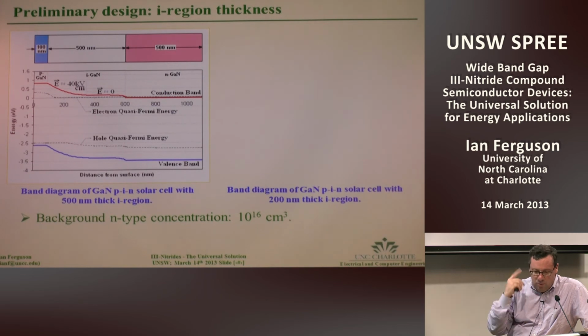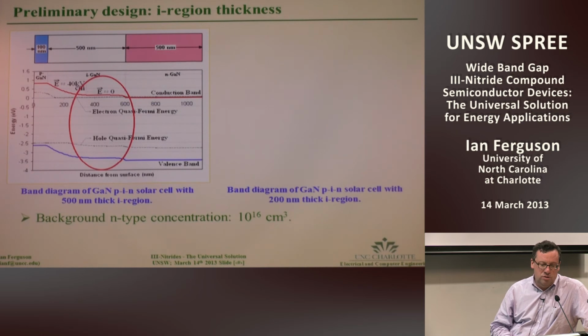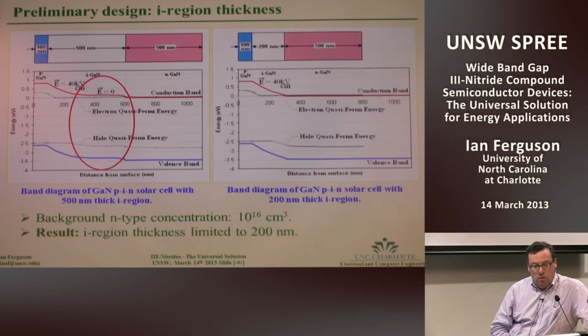What else did we use? I'm a little bit tired, so the name will come back to me later on. So typically what you would find is that your depletion zone was about 0.2 microns or so within most of these devices. So you had an issue, almost independent of composition, that you had to get all your absorption within that 0.2 micron region.